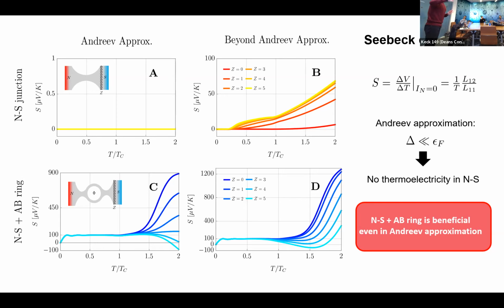Now, the story completely changes when we do take into account the presence of the ring, so panel C and panel D. Especially in panel C, meaning within the Andreev approximation, we already obtained a Seebeck coefficient which is finite, and it can reach orders of magnitude like hundreds of microvolt per Kelvin. And even better, if you go beyond the Andreev approximation, panel D, we can get a Seebeck coefficient of the order of millivolt per Kelvin, which is quite impressive considering that here we are dealing with superconducting components. So the second take-home message from this slide is that the combination of the Aharonov-Bohm ring with superconducting materials is beneficial for the thermoelectrical properties of the system, even if you're considering the system in the Andreev approximation.